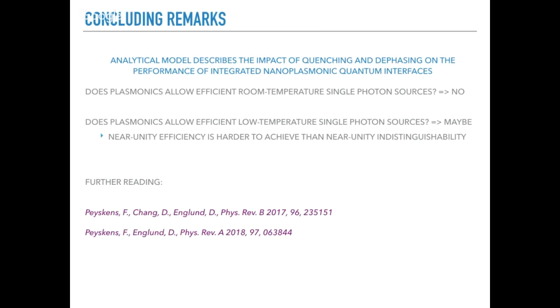Because silicon nitride is low loss for the visible. A lot of these 2D emitters emit light in the visible regime. So we can guide them with low loss, and we can make ring resonator cavities with them, or DBR filters on a chip. So we can have both enhancement of our quantum fluorescence and on-chip filtering, to get rid of the excitation light on the chip. That is work going on, which is also in collaboration with Pablo's group. So we're now in the first stage of trying to put some of these ideas into practice.